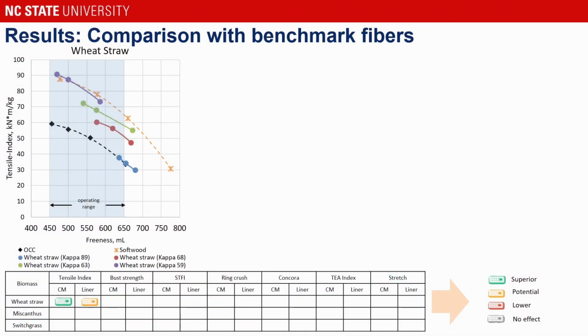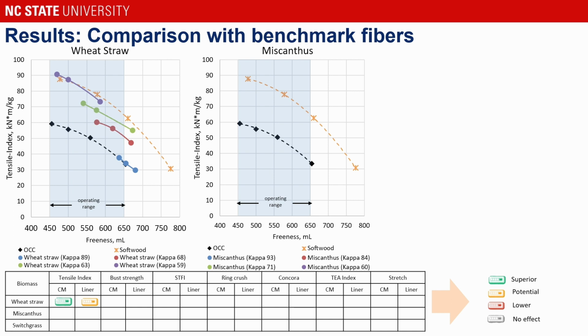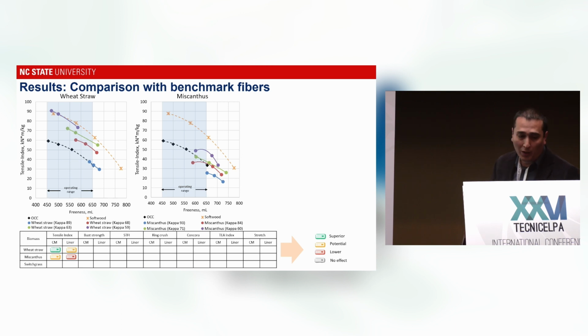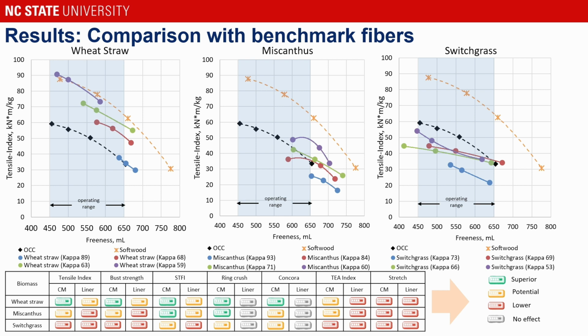So it's important also to mention that maybe one concern is the drainability of those pulps in the paper machine, and we know that these properties depend on the refining. So in this study, we are considering an operating range in order to improve the properties by refining. So let's see what happened with miscanthus. We have seen here the same behavior, a little lower than the benchmark fibers, and for switchgrass, we had seen lower properties than OCC. What is interesting is that we evaluated all the main properties for corrugated medium and liner. We see that those fibers have the potential to be used at least in corrugated medium.